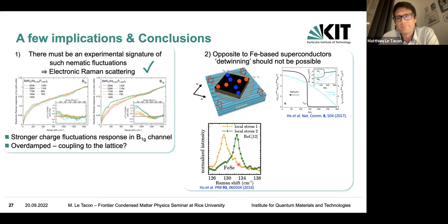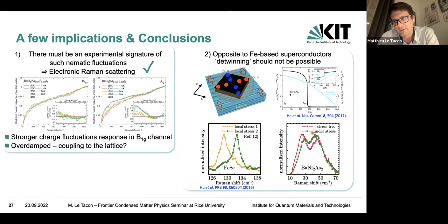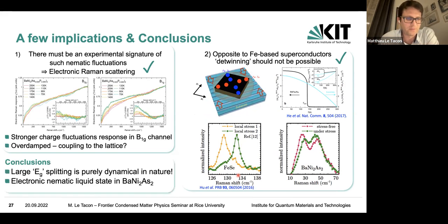You can probe that. Now, the way we tried to do that here in the nickel-based compound is to use this fiberglass substrate, which has an anisotropic thermal expansion. So we glued our nickel 122 sample on that, and we did the Raman measurement, and we see what happened. And what happened is that basically we do see a small redistribution of the spectral weight, but we are not capable of getting a fully polarized nematic state, if you like. And the reason being that we cannot detwin the system because it's not ordered, right? So you do break the symmetry with your external strain field, but there's nothing to detwin per se.